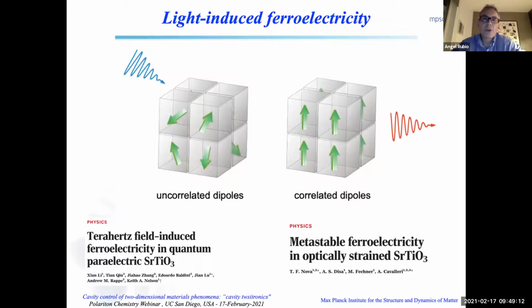Then the argument is the following, and then you will understand why I'm interested in this, which is very similar to what we were discussing before. In a paraelectric, you have domains in your system, and each domain has its own dipole. This dipole is randomly distributed all over the sample, and on average you get zero electric moment, which is basically the argument for calling it uncorrelated dipoles. And what you want to do is, if you come with a strong light, find a transition in which you align those dipoles. And this is basically what you will call the quantum paraelectric, or paraelectric to ferroelectric transition.